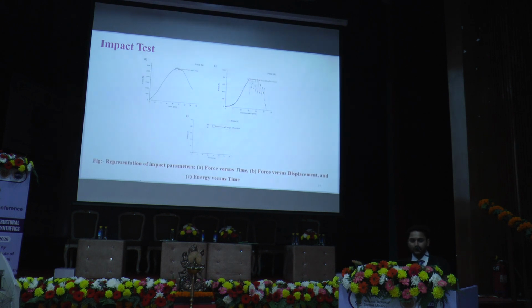In impacts we assess force versus time, force versus displacement, and energy versus time, and these are the impact test results of all 12 samples. We found that Dyneema Kevlar based interlayer hybridization along with carbon layering provides a 3078 peak force, and Dyneema Kevlar plus Zylon Kevlar interlayer hybridization shows a 3692 peak force. Mostly the samples with carbon combined with Zylon and Dyneema provide a higher peak force and displacement, and also the total energy absorption with a minimum thickness.